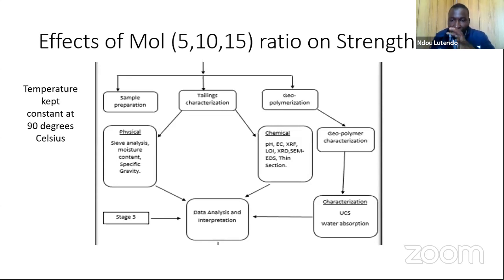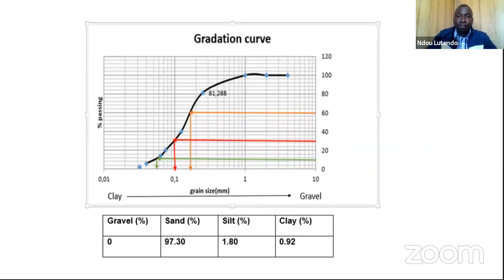After geopolymerizing my tailings, I characterized the geopolymer to compare the before and the after. Number one, I did the UCS, which determines the strength. Hence, I'm confident that the geopolymers have more strength than the PPC cement. And I did water absorption just to see its reaction to water. Then that's when I was concluding my studies.